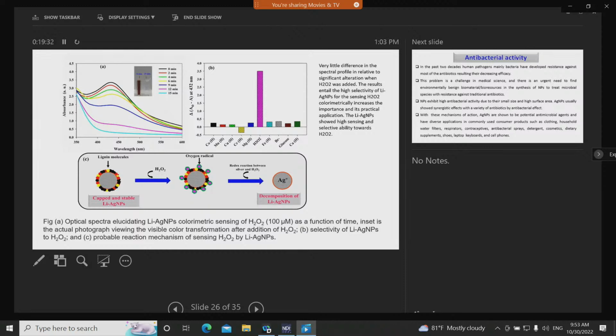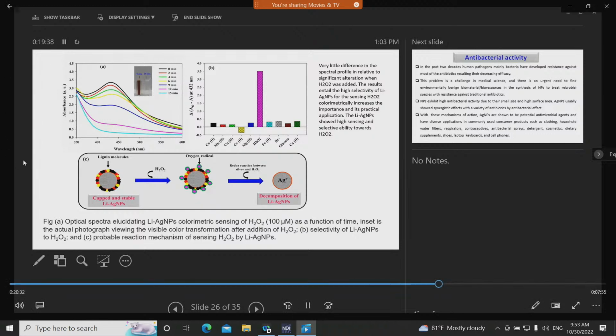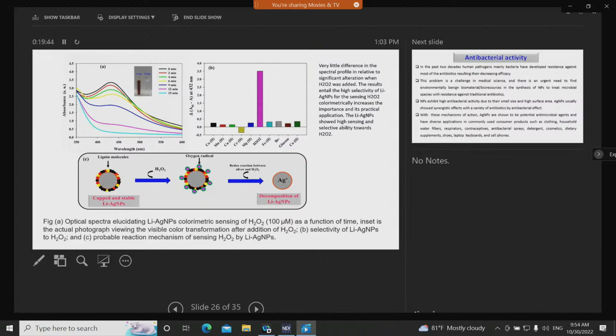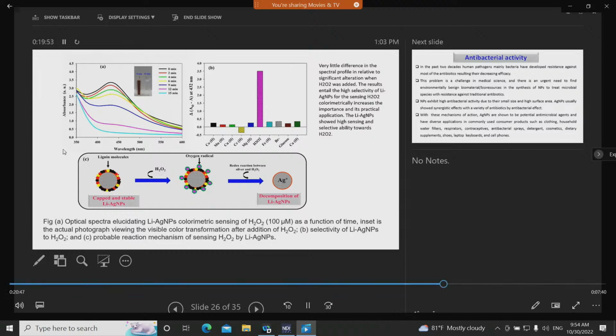Now this figure, here we can see the probable reaction mechanism of sensing H2O2 by lignin-silver nanoparticles (Li-AgNPs). So it was supposed that after addition of H2O2, it produces highly reactive oxygen radicals which disrupt the LiAgNPs and lead to the aggregation of the nanoparticles.